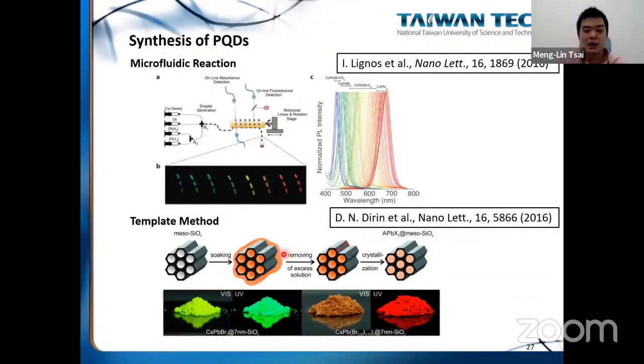Other researchers try using a template as a synthesis medium. You can see that the perovskite quantum dots can form within these mesoporous materials, so you can achieve a uniform size of your perovskite quantum dots.